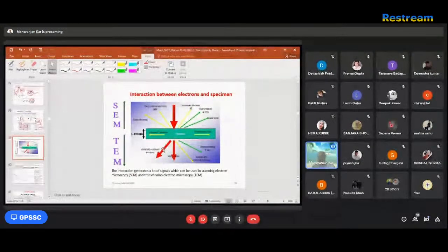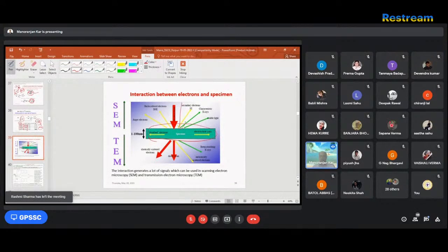Very interesting. I told you the second question: what microscopy can we build? Listen carefully. Within 2 minutes, I'll make you understand. Very simple. When the electron is coming, you have a sample, and the electron is bombarding it. The electron does not understand what is happening; everything we do is formulation. When it interacts with the atom, what will happen? Some of the electrons will pass through if the sample is less than 100 nanometers. If it is 50 micrometers or 1 micrometer, no electron will pass through. Zero. So if it is less than 100 nanometers, some of the electrons will pass through. This area is the electrons transmitted through your sample, and some of the electrons will be in this area. These are basically your reflected electrons.